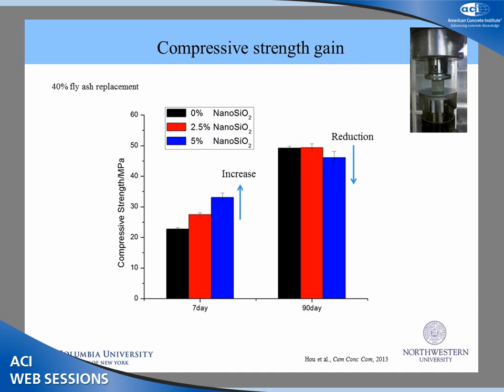But at the later age, we see that the rate of strength gain isn't significant, and even at 5%, there's a slight reduction. Now, from a practical point of view, this isn't a critical concern, but we're still interested in understanding why the nanosilica, although it's improving early age strength gain, is having little or even a slightly detrimental effect at later ages. Now, if you think about the system, there are two components that are competing for calcium hydroxide, the nanosilica and the fly ash, because they're both pozzolanic materials.